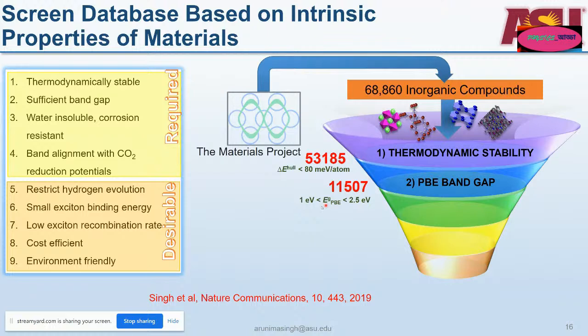So we selected a range which was representative of that underestimation in band gap, but still could give an idea of materials which would be in the visible part of the solar spectrum, which constitutes a major fraction of the solar energy. We found about 11,000 materials. And these two properties were already there in the Materials Project database. So the Materials Project database was monumental in shortening down the list from 70,000 to 11,000.